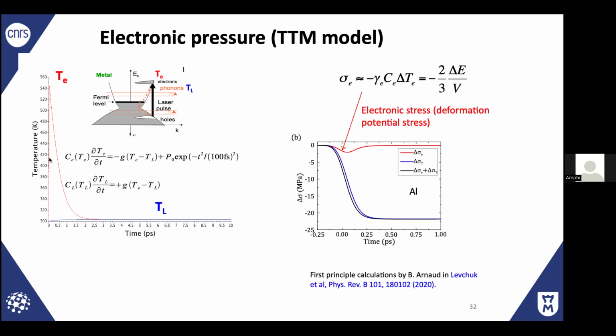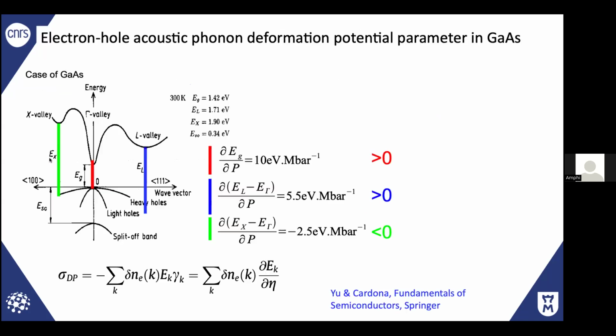But during that time, where the hot electrons still exist, there is a stress, a pressure, just because it's as if the Fermi sphere has expanded. This is electronic pressure. So if you put 1 eV per electron, for example, you reach the gigapascal range. It's very important. So this is what we call electronic stress.